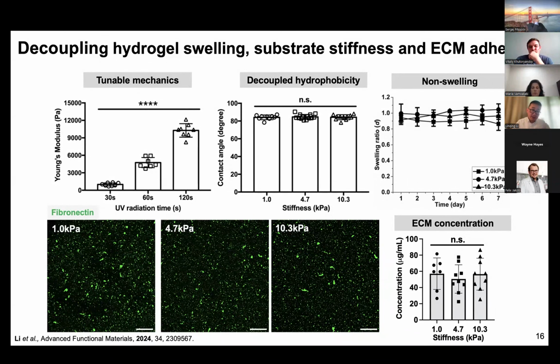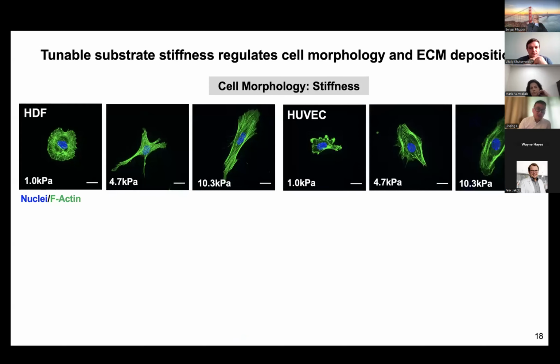And then the determinant of how much fibronectin is absorbed on the surfaces is not the mechanical properties, it is the hydrophobicity of the substrate, which is determined by the contact angle, which is further determined by the methacrylation degrees. So now we generate a category of hydrogel surfaces that can really decouple your biochemical signals from the biophysical parameters. We're using this to understand how changing the stiffness regulates cell behavior, while not simultaneously changing the biochemical signals.